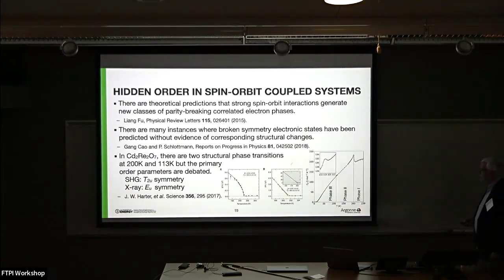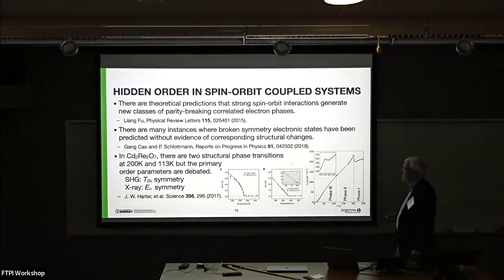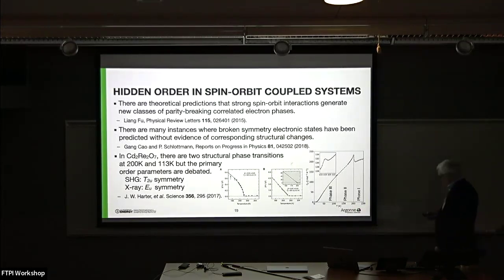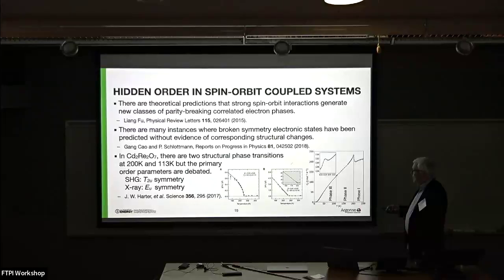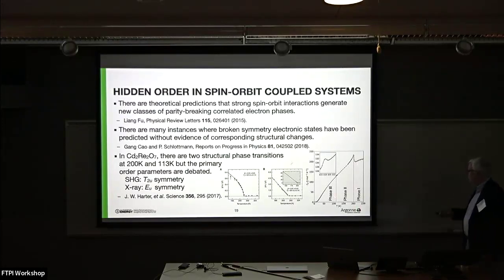In cadmium rhenate, the peaks had actually been seen, but there was a dispute about what the primary order parameter was. David Hsieh had done second harmonic generation spectroscopy, and his claim was that the primary order parameter was not the Eu, which earlier diffraction results suggested, but the T2u. There were two transitions in this material, at 200 Kelvin and about 115.